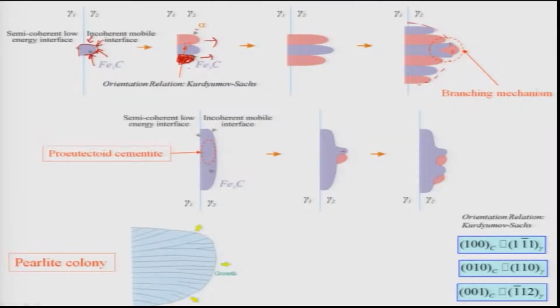That is what is seen here. This cementite which is there can nucleate very easily, and because of that it can have a certain kind of structure like that. Once it goes into the gamma grain, it requires more carbon, so carbon will diffuse from the nearby region, and the nearby regions will become lean in carbon concentration. This will allow you to nucleate alpha phase very easily on both sides of the cementite, and this will again lead to formation of colonies.